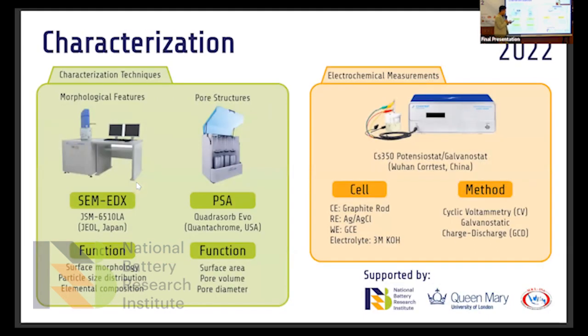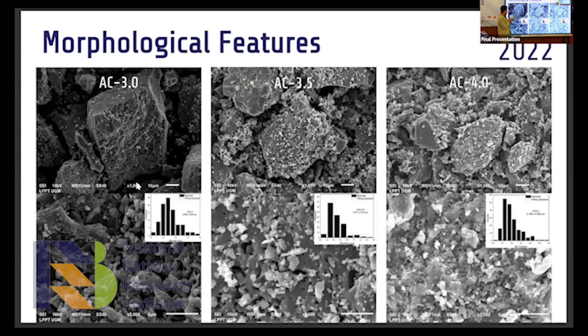Next. As for the characterization, we use SEM-EDX to study the morphological features, as well as PSA to analyze the pore structures. CV and GCD were also conducted to finally evaluate the electrochemical performance. Next. Here is the result for SEM. The image showed the degradation of the particle size as the activation time increased, inversely proportional to the dominant pore diameter. AC with a longer activation time broke the surface particles, covered the preformed pores, and resulted in a smaller pore size. This result assumes that samples activated over 3 hours will have a smaller pore distribution.